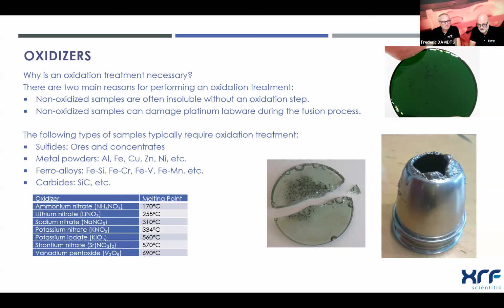Clearly the most used, like you explained already, is lithium nitrate, because lithium is not analyzed, so it's not contaminating the samples. The problem with lithium nitrate is that it's a really hygroscopic compound, and so if you leave it unattended on your bench, it quickly becomes liquid. And even in the flux, if you leave the pot open, you can have some agglomeration in the flux pot. So it's something you really need to pay attention to, and keep dry. Yeah, exactly. And it's why the lithium nitrate is often used, because it's like a sugar and it's very well mixed with the flux. Both are available integrated in the flux, but you need to know that with lithium nitrate there are some things you need to take care of, and the fact that you need to dry it. And of course, if it's really complicated, you can mix oxidizers together to improve the oxidation process.